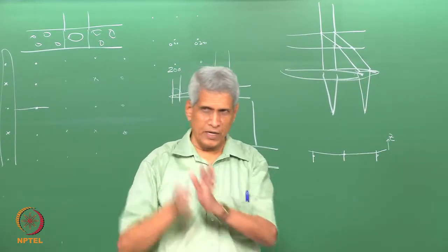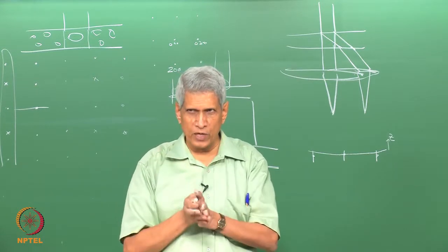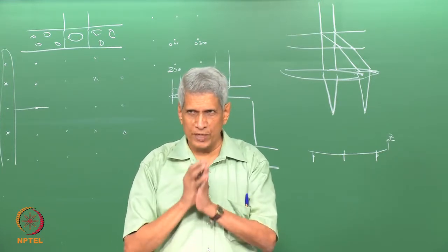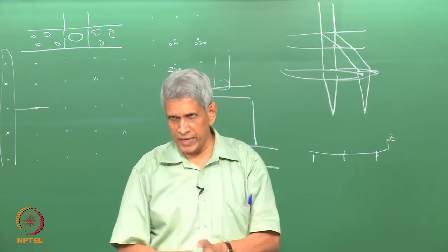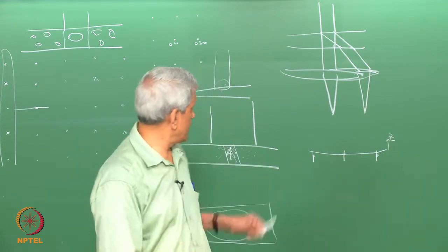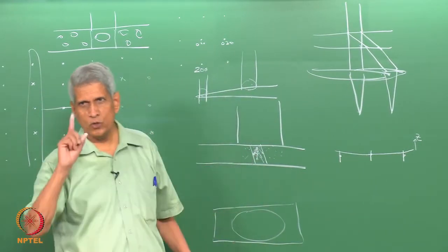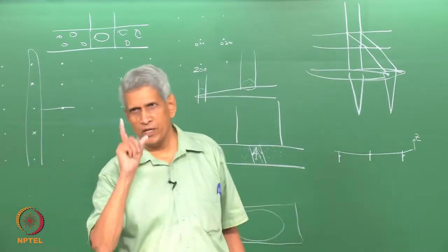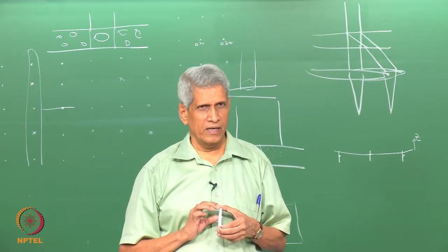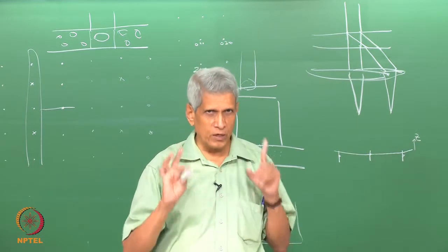That is why the tilting of the Kikuchi band is very sensitive to sample tilting. We can utilize this to find out the deviation from Bragg angle, and also to orient the sample correctly. The separation between them is very accurate because the Bragg angle is satisfied exactly at this particular theta value. So, this could be used to find out the lattice parameter very accurately. These are all the three applications of Kikuchi diffraction. Is this clear?